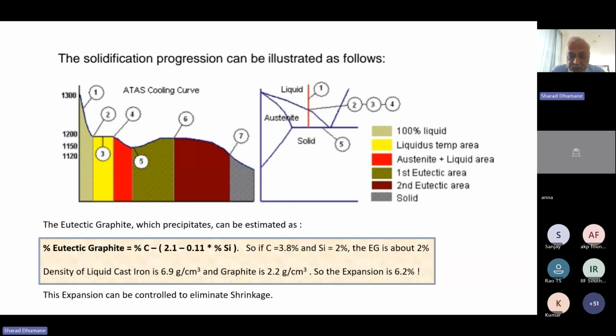So what happens when this graphite comes out? First thing we look at is how much graphite actually will come out, because that is very important. The more graphite that comes out, the more beneficial it becomes for us to take action on the solidification shrinkage. So this is a very important point. We have to understand that when ductile iron or grey cast iron solidifies in a mushy zone or a freezing range, graphite comes out. And because graphite comes out, there is an associated impact on the volume of the liquid, which we are going to discuss. But right now, we just want to understand how much